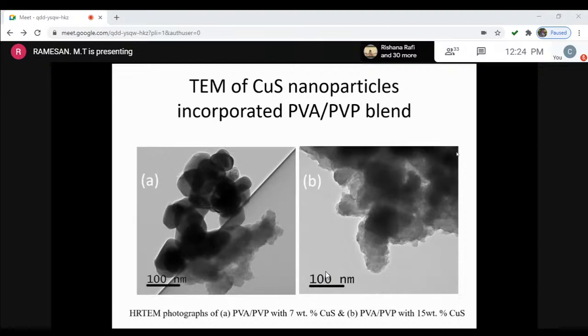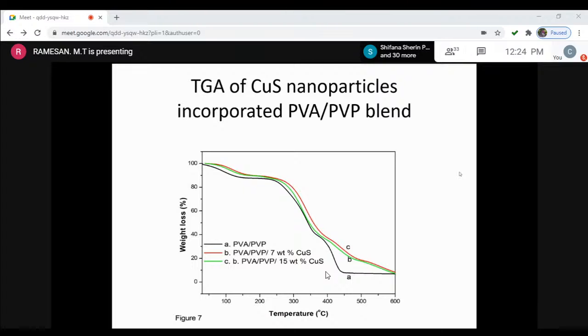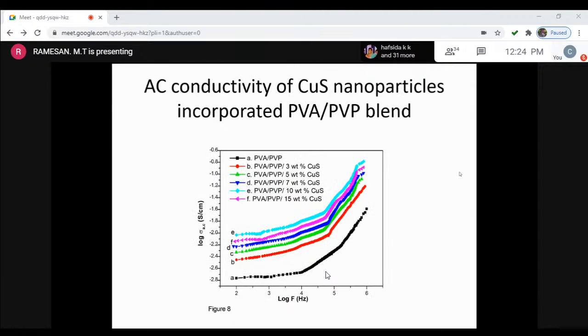These are the TEM images. You can see that these copper sulfide nanoparticles are spherical or hemispherical particles at the lower loading. At the higher loading, these particles become agglomerated. This is the thermogravimetric analysis, which gives an idea about the thermal stability of that system, and thermal stability is increased with increasing loading of copper sulfide. We know that copper sulfide metal particles have very high thermal stability, so it can impart better thermal stability to the PVA PVP system. This is the AC conductivity. Copper is a very good conducting material, so conductivity can be imparted into the PVA PVP system.